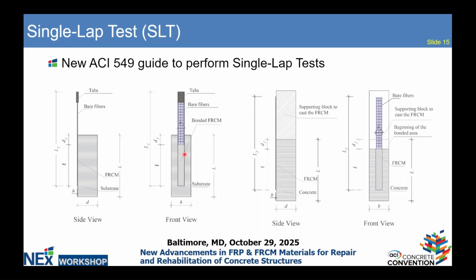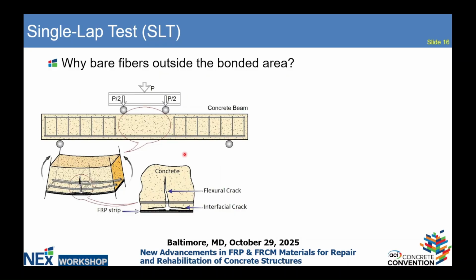I want you to note that the fibers are bare outside the bonded area. So you use the matrix to bond the fiber for the length that you want to test, but then the fibers are bare outside. And the reason for that is in this picture. So if you're familiar with FRP, whenever there's going to be a flexural crack in a beam, the crack will then determine a propagation at the interface with the FRP.